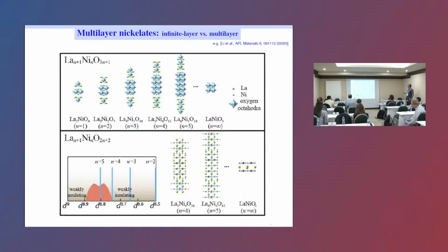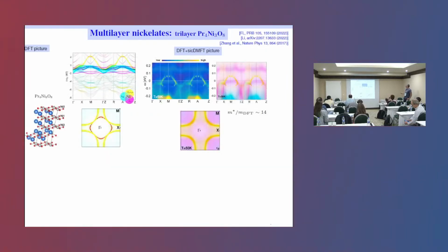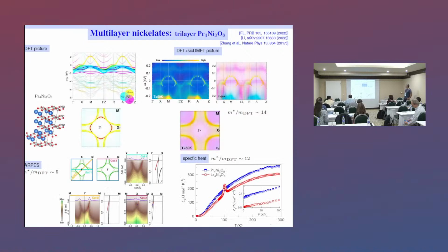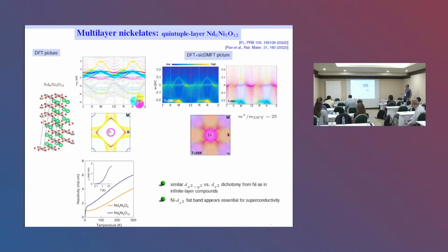If I have a few more minutes, I can also extend a bit to this multi-layer compound. So this was already put forward. If we go to the multi-layers, which can be more easily produced in experiment, if we raise the number of layers, we come from the overdoped region and enter the superconducting dome via more and more layers. And we did calculations on this. Maybe let me skip this, which is for the 3-layer compound, which is a bit different physics. But maybe on my last slide, just to conclude in good time, look at this 5-layer compound with the same machinery.